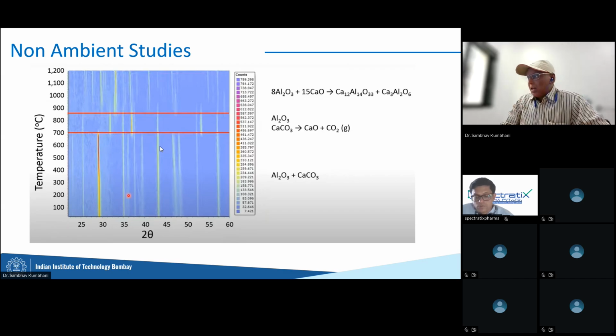Now the way you read the spectra is, if you notice this peak, let me put it this way: all the peaks below this 700 line are for calcium carbonate. This peak, this peak, this peak are all calcium carbonate peaks, because after 700, calcium carbonate decomposes and forms calcium oxide and releases a lot of CO2. And once calcium oxide is formed, these new peaks are for calcium oxide. This is calcium oxide, this is calcium oxide, and this is calcium oxide. That's it. Whereas the ones that are crossing the 700 mark and remaining constant from room temperature all the way up to 900 are all aluminum oxide peaks. So this one is aluminum oxide, this one, this one, this one, and this one as well.